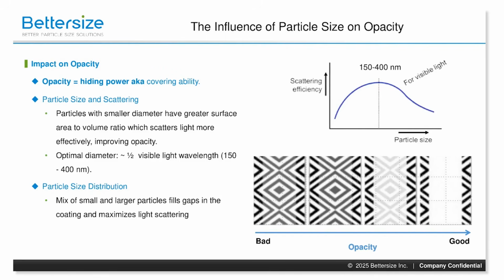Particle size distribution: with a well optimized distribution, you can get a mix of larger and smaller particles, and this can improve hiding power by maximizing light scatter and filling gaps in the coating. So, in summary, smaller particles generally enhance the hiding power of the coatings by scattering light more effectively, while larger particles contribute less to the opacity. But optimizing the particle size distribution is key to achieving the desired level of hiding power within these materials of inks, paints, and coatings.